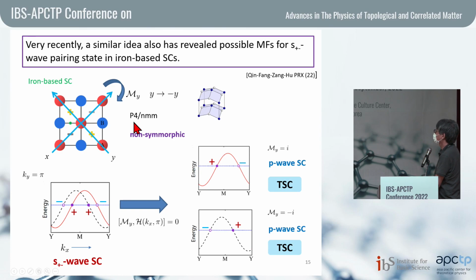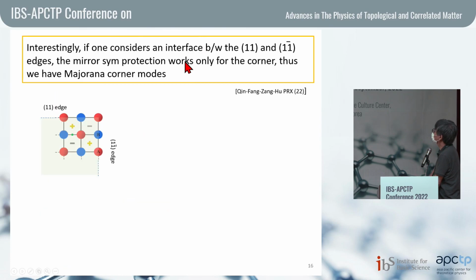However, more importantly, if you consider the particular edge, then we can obtain the Majorana zero mode. Here I show again the crystal structure of this material, and here I consider the (1,1) edge and the (1,1 bar) edges. As I mentioned before, this crystal structure has a mirror reflection symmetry with respect to this axis. As you can see, these two edges are interchanged by the mirror reflection symmetry. So we don't expect any surface state produced by the mirror reflection symmetry for these two edges.